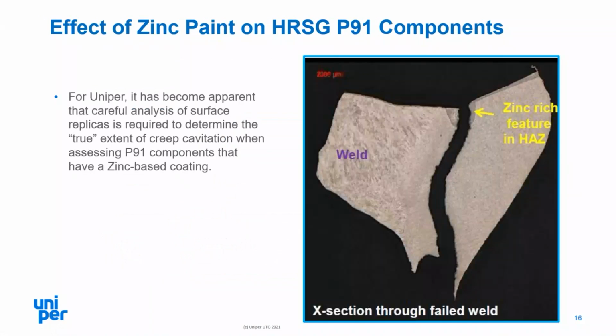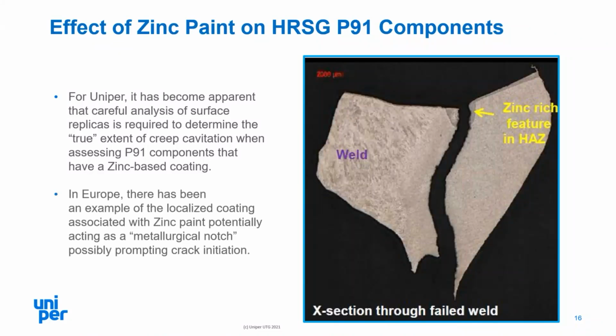So for ourselves within Uniper, the Technology Centre, it became apparent that we required careful analysis of the surface replicas that we were obtaining, not only to identify whether there was a presence of a dark band local to the weld, but also to understand the true extent of the creep cavitation that was being seen there. This was reinforced by an incident on the European mainland, where an example of the localized coating associated with zinc paint seemed to act as something of a metallurgical notch, potentially prompting or initiating a crack from the external surface to go through the component.